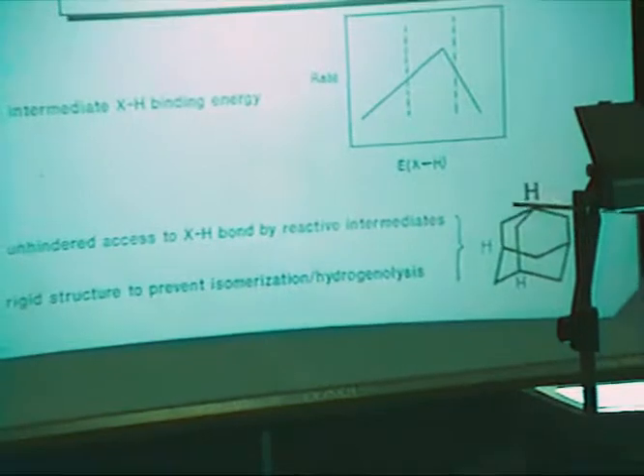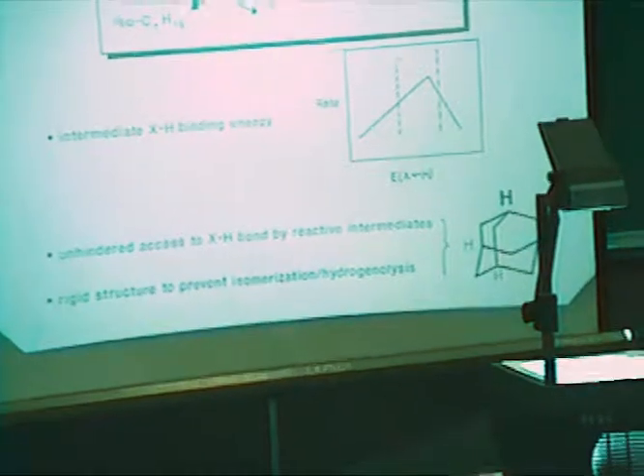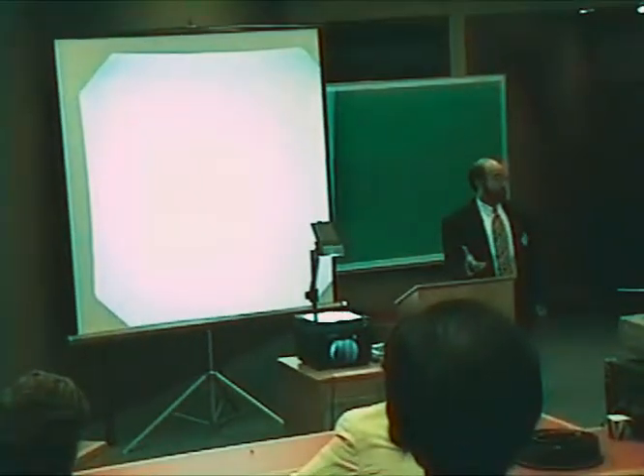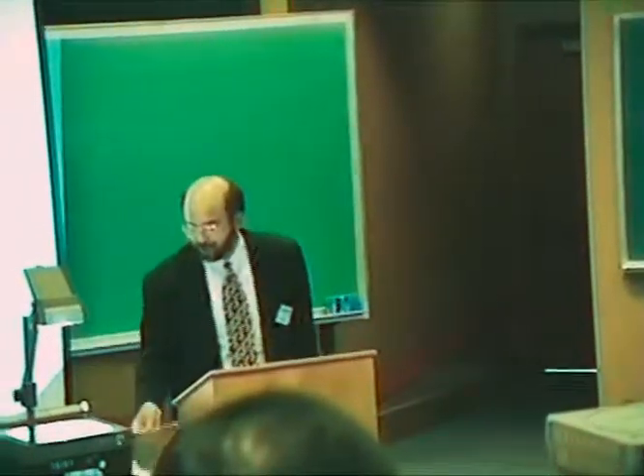First of all, suppose that you want to come up with a co-catalyst, and that co-catalyst is one that you want to use in order to get a hydrogen from one place to the other one. What should you look for? And the concepts of catalysis begin to show us what we should be looking for. One of these steps has to form an X-H bond, and one has to break it. And in order to be able to cycle around here without much destruction of that species, I need to be sitting where the energy of that X-H bond is neither too low, so I form the bond, nor too high, so that I never break the bond once I have made it. So somewhere in here I want to be. I want also a catalyst where I have access to that hydrogen and not be restricted by any steric effects. And I also want, if I truly want a co-catalyst, something that does not get consumed or destroyed as part of the overall cycle.